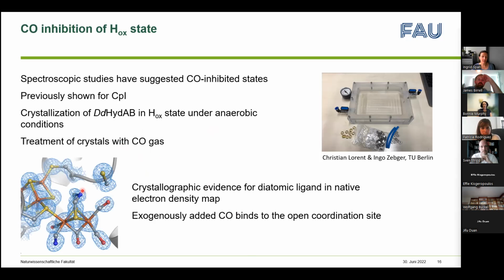So this is the resulting crystal structure that we obtain. And within the electron density map, we see evidence for a diatomic ligand. And we propose that this is the exogenously added CO that binds into the substrate binding site, so the same site where the thiol binds, or the hydrogen substrate.